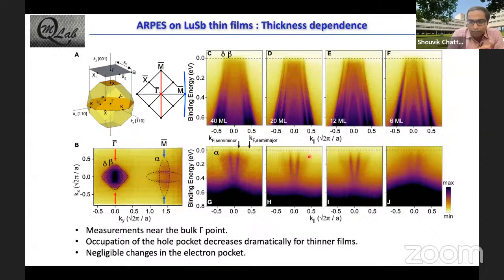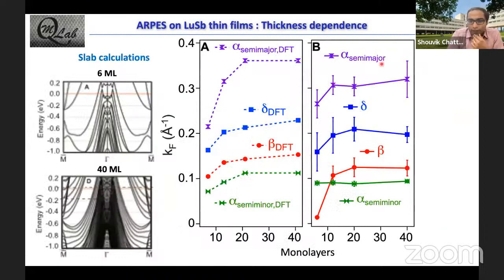We can do it a little more quantitatively, as I'm showing you here. So this is our data, and you can see that yes, the hole-like pockets, this beta and the delta, go down, but the electron-like pocket does not change that much as we grow thinner. So we try to understand that by doing slab calculations where you can mimic the electronic structure of ultra-thin films. But we find that this does not really match our experimental data. You can see that the alpha semi-minor also reduces as you go down in thickness.